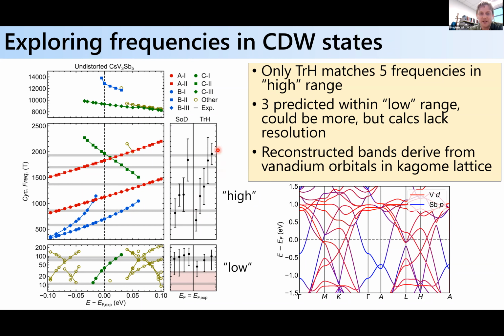Furthermore, we can identify from these models that the orbits we observe at low frequency are due to reconstructed vanadium orbitals, which are endemic to the Kagome lattice. So this is the first experimental insight that the charge density wave state is being driven via the vanadium orbitals in the Kagome lattice. And so it supports the use of some of these more minimal models, looking at just the physics inherent to a Kagome lattice, driving some of the interesting properties of these systems.